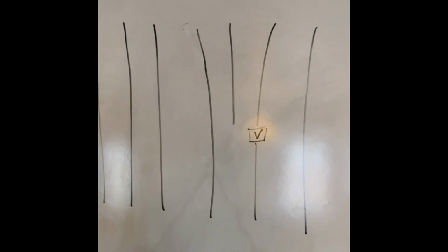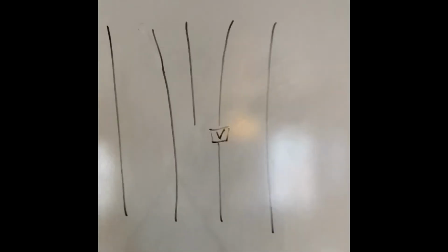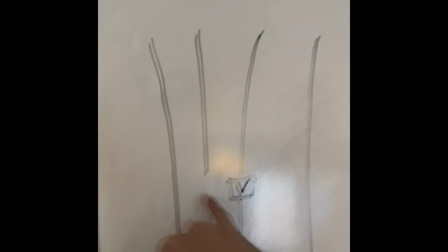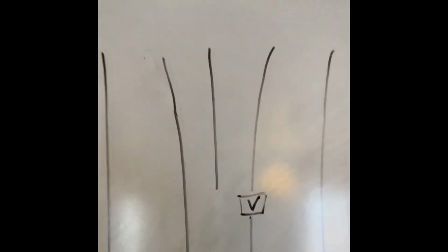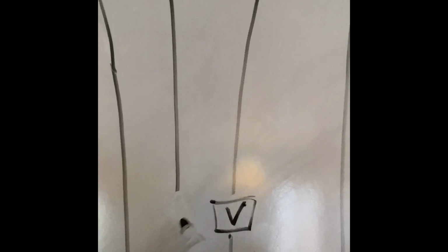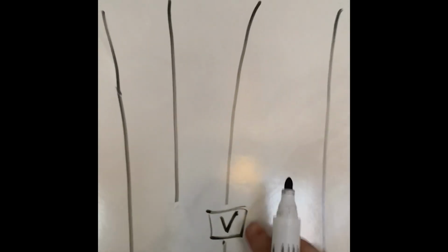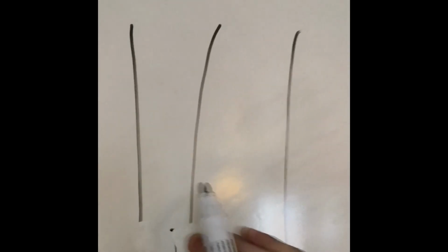While dislocation climb was not visible in my bubble raft practical, I did see extra half planes, the edge dislocation running here, remove vacant sites, as when these dislocations move and come into contact with a vacant site, this will move and remove that vacant site as it joins to the base of that dislocation line.